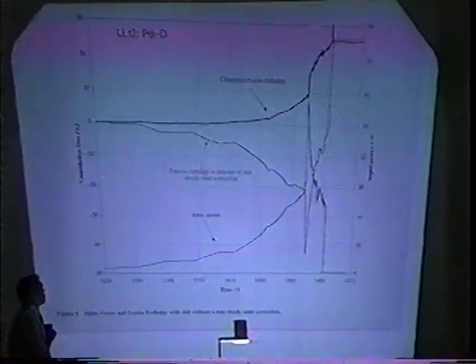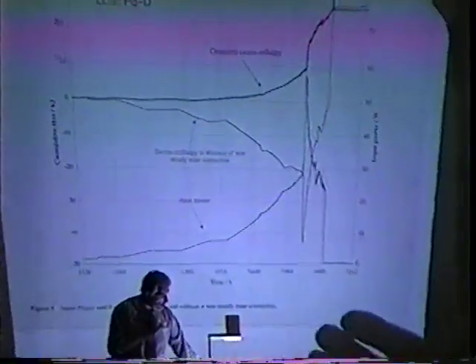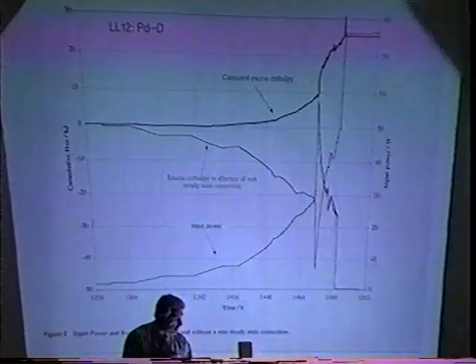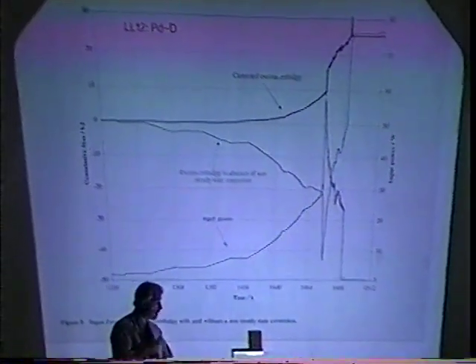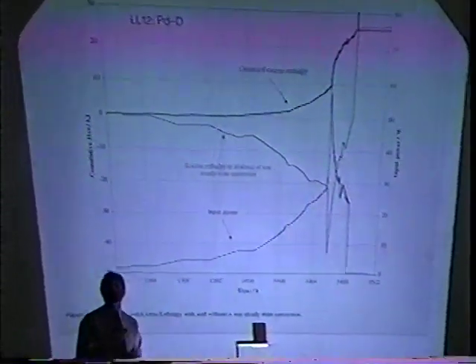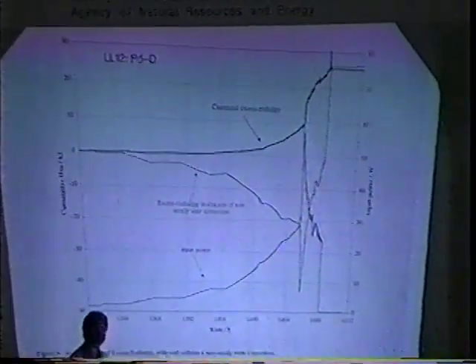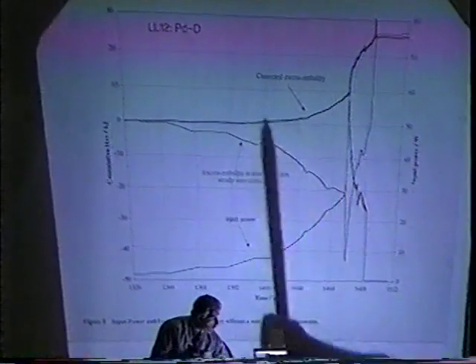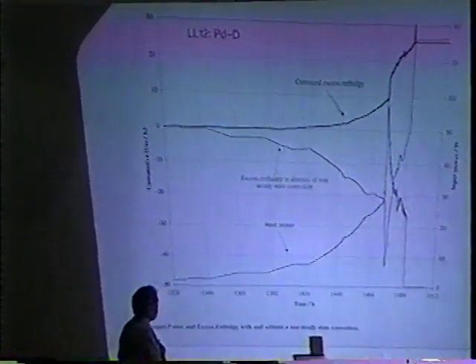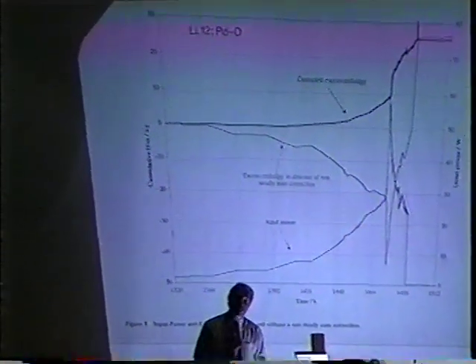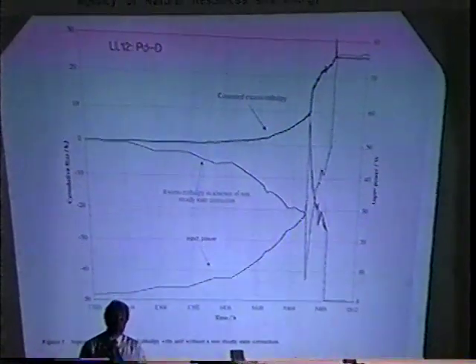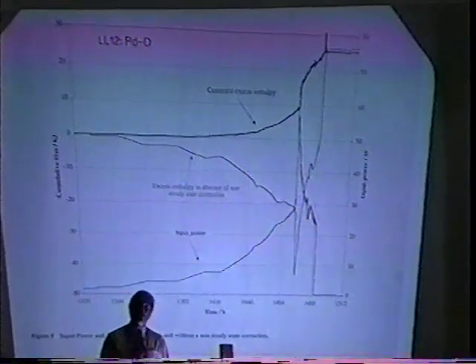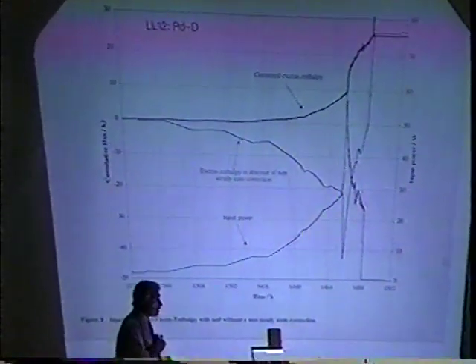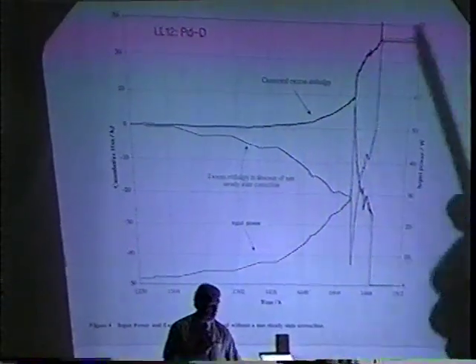What I have here is the result of one case where we observed with some confidence excess enthalpy. The blue line is corrected for non-steady state effects. The green line is uncorrected, but obviously the enthalpy goes from 0 up to something like 25 kilojoules in a relatively short time during the boiling of the calorimeter. The boiling period is from about here to here. Without the non-steady state correction, it's very difficult to get an idea of the temporal response of the excess heat. With the correction we can fairly accurately characterize the enthalpy time profile.